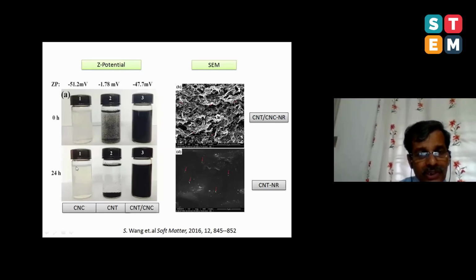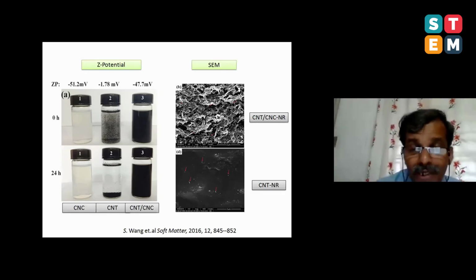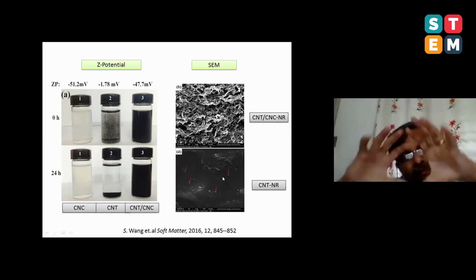If you look at nanocellulose suspension in water, at 0 hour and 24 hours, you see this is extremely stable. After 24 hours, there is no settling down of nanocellulose particles. Look at carbon nanotube in water, if you keep it for 24 hours, all these carbon nanotube particles will settle down. But if you make a hybrid of nanocellulose and CNT together in water, look at this. After 24 hours, no settling down. So CNT aggregation will be suppressed by nanocellulose. And this we found in natural rubber. Look at natural rubber, CNT, nanocellulose combination, excellent dispersion of CNT. If you just put CNT alone in natural rubber, all the CNT aggregates.